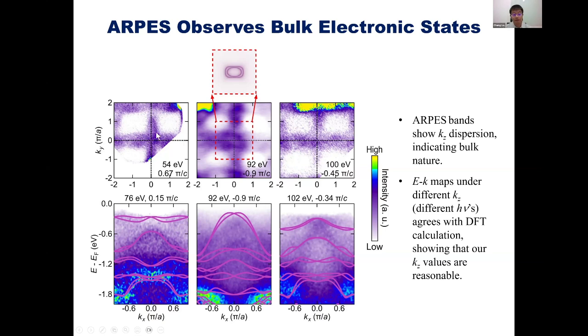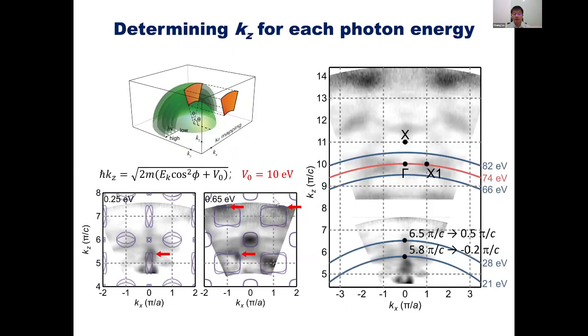Although the intensity here is a little bit broad, we can see that this has a cross-like shape here, and this has something like an ellipse. So it changes from nothing to an ellipse with different photon energies. So we believe that we are actually probing the bulk bands. Here are the details, we skip that.